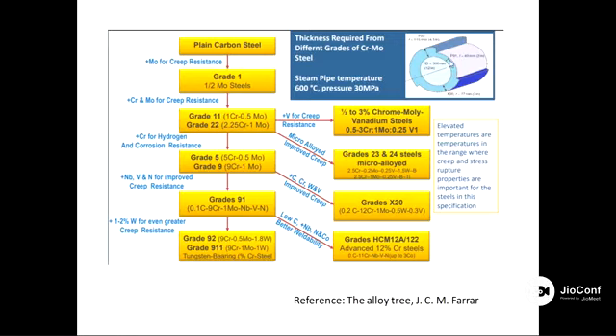But if the same is produced with a P91 material to meet this application, service temperature, and pressure, it could be used with only, say, 50 mm. So you could understand the role of alloying elements, right? This chromium, molybdenum, tungsten, and some microalloying elements can reduce the thickness required for a different grade of chromoly steel. And chromoly steels are extensively used for elevated temperature applications where creep resistance and stress rupture properties are required. So by this slide, I wanted to give you an idea about the role of alloying elements, right?